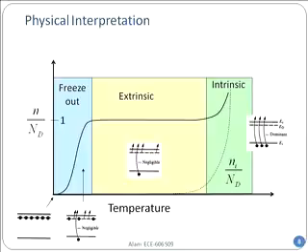At some point it can easily overwhelm the number of electrons from the donors. That's why the n_i of the material can exceed the donor density, and that's when it takes over and it's no longer a doped semiconductor per se. It's like an intrinsic semiconductor, because at that temperature the electron density doesn't know about the donors anymore.